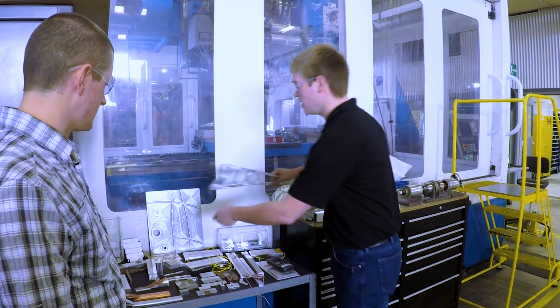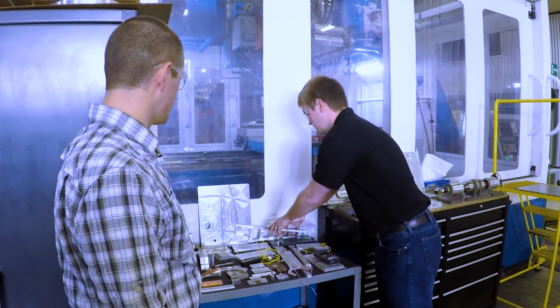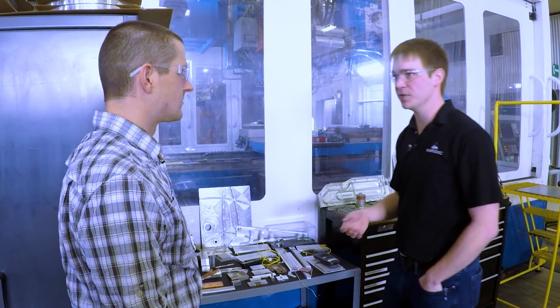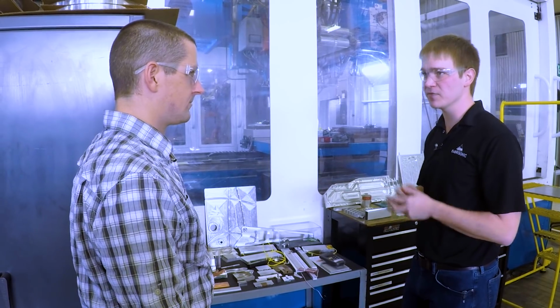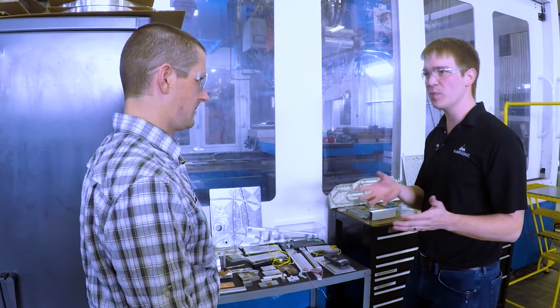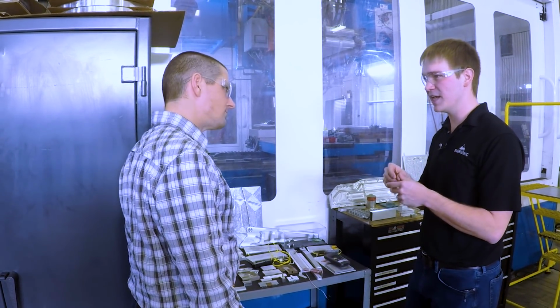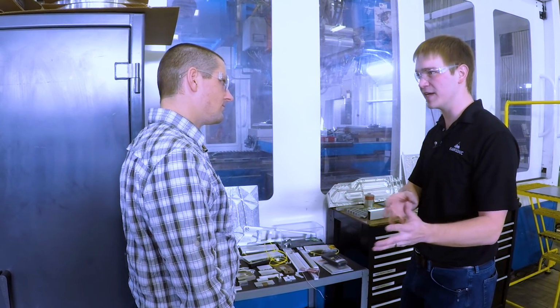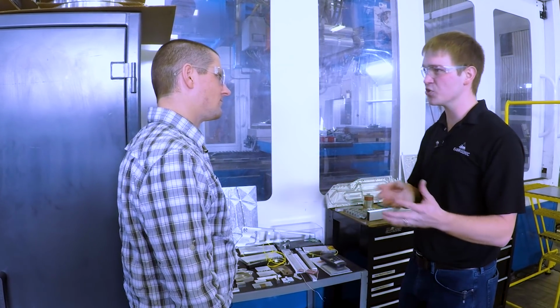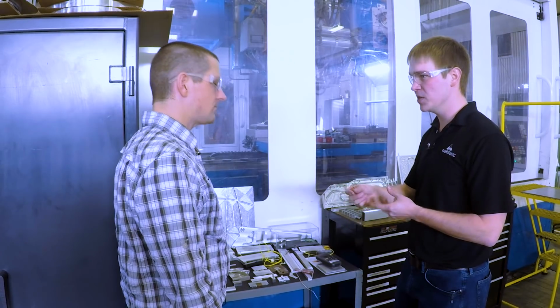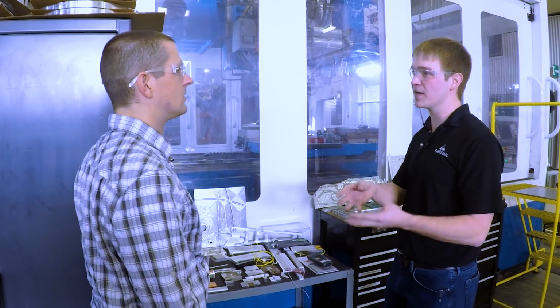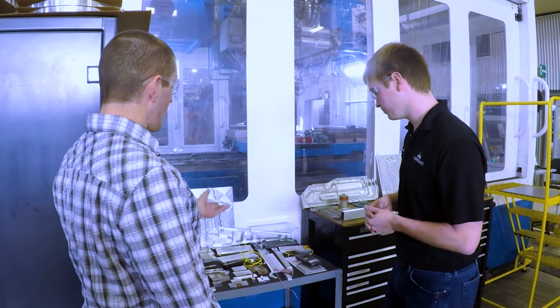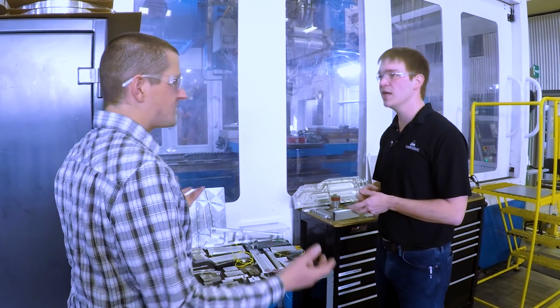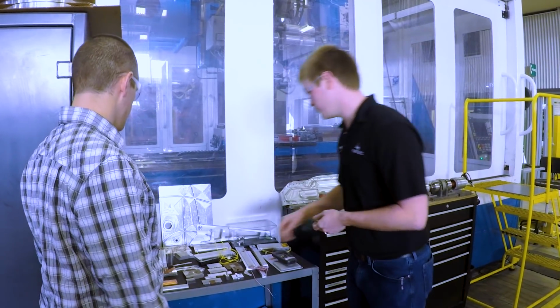And we actually did lab tests on it to measure the life of the fiber in crack propagation. And it's just amazing the data that you can get out of such a fine sensor. And even when we put it in there, it's so small that it has like no detrimental effect. Normally, if you were to put any other strain sensing device onto a piece, it would be so large that it could affect the life of the part. Right. Well, and you don't have to take the part out of service to get this real-time data. Exactly. You just connect onto it.